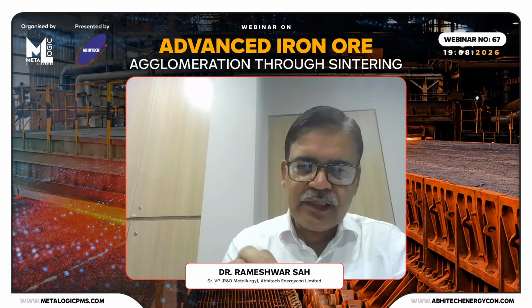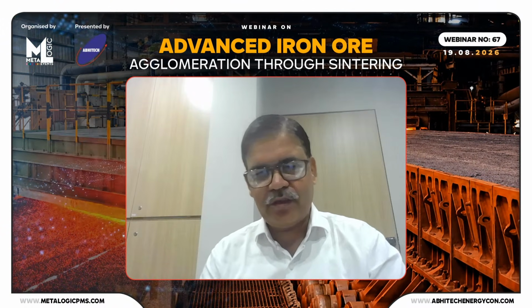So whatever the fuel requirement for goethite ores, we can take care of that. If any loss on ignition generates some vapor or moisture, that can be taken care of while it goes through the ECP process. So this blend optimization has to be done, and that is normally done while bedding for sintering. So that could be taken care of. But if it is disproportionately very high, then we have to go for an entirely different set of calculations for the sintering process. Thank you.